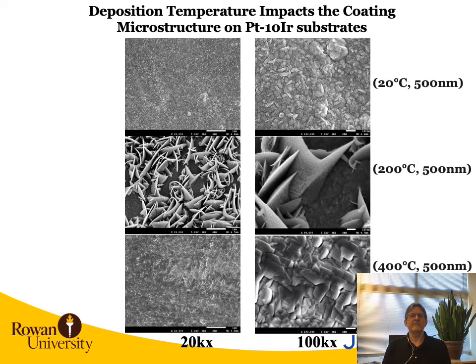We made coatings at various temperatures, 20, 200, and 400 degrees Celsius, and they were all targeted to be 500 nanometers. If we look at the lowest temperature depositions, you see this sort of small grain that was reminiscent from what we've seen in the earlier slides. Then at 400 degrees, you see what look to be larger crystallites forming in the coatings due to the larger temperature and the higher mobility of the atoms when they're landing on the surface.